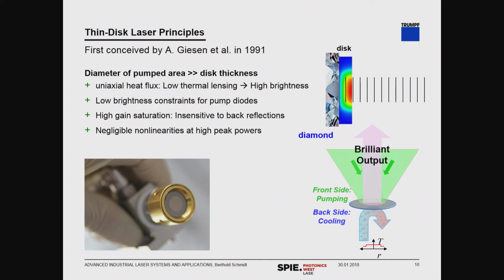And I already mentioned the low brightness constraints of the laser diodes. The laser operates at a very high gain saturation. So when you have a CW laser at 6 kilowatt, the output coupler has a reflectivity of 97% in the range, which means there are 194 kilowatts stored in the cavity. This makes the disc laser very insensitive to back reflections, thus a very robust industrial laser for cutting all types of steel and materials. And the negligible nonlinearities are in particular helpful for achieving very high peak powers, as you will see in just a few minutes.